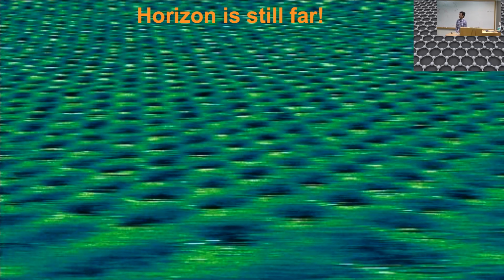So these Moire patterns are created on a graphite surface. Yeah, so it's multiple layers. And I don't make them. They are naturally found on the graphite surface and they're formed during the exfoliation. If you buy bulk graphite and try to image them, you're probably not going to find them. If you exfoliate them for a while, then they are formed on the graphite surface naturally. And I think it's the only material that I know of that naturally favors the formation of moires. So it's a good platform to study moire patterns with.